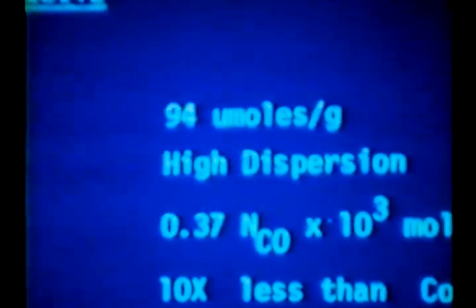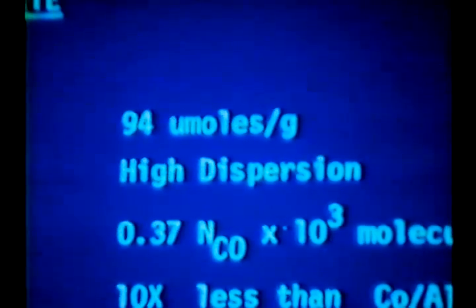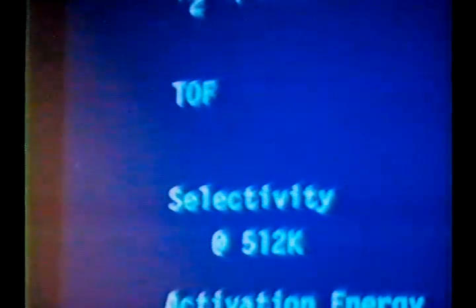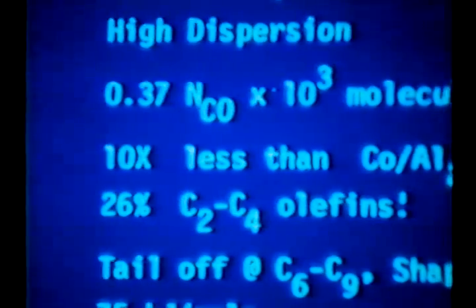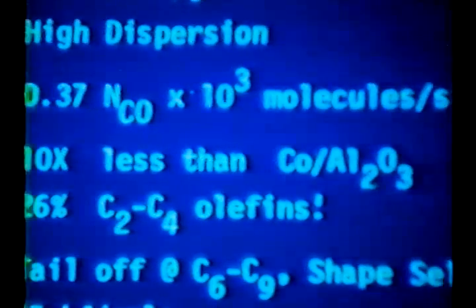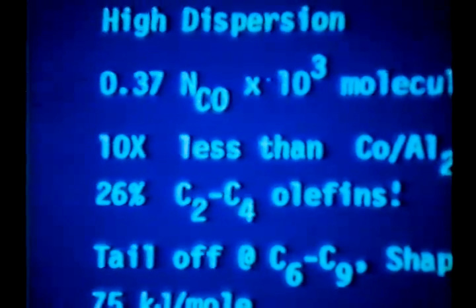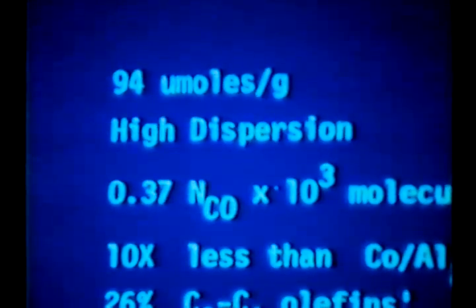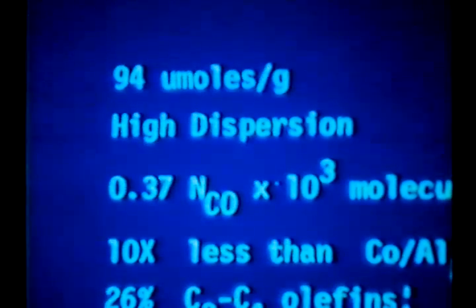Well, gee, this is a catalytic center. We should talk a little about catalysis. How does all this relate to catalysis? And I think with all the techniques we've hit this with, those metal particles in the plasma are really small, 5 angstroms or so. And one of the first things we did, and this is work in collaboration again with Cal Bartholomew, we looked at hydrogen uptake, hydrogen chemisorption, at 94 micromoles per gram, essentially 100% dispersed, extremely small particles.